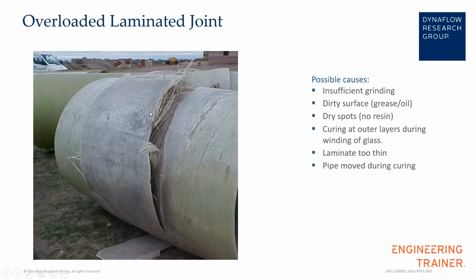For example, for this large joint type, to create the outer laminate it may take a total time of maybe 45 minutes to do the winding. To create sufficient thickness, maybe you need to wind around the pipe 30 times or 40 times. That can take, for example, 45 minutes. If the curing of the resin starts, and it also depends on the type of resin, polyester or vinyl ester, when it starts curing, then it generates heat and it accelerates the curing of the other layers, of the more outer layers also.